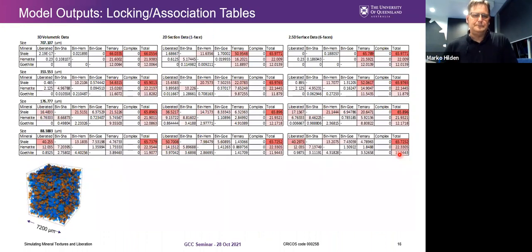As mentioned before, it produces these association tables in 3D, 2D, and 2.5D as well for different sizes, just showing a small number here. But you can see that at a coarse size, most of the particles are, in this case, ternary. As you get finer and finer, they become more and more liberated, and the ternary particles become fewer and fewer.